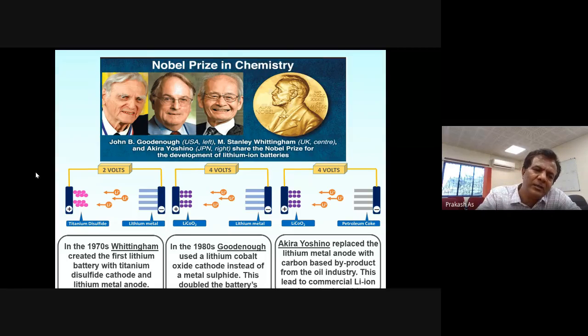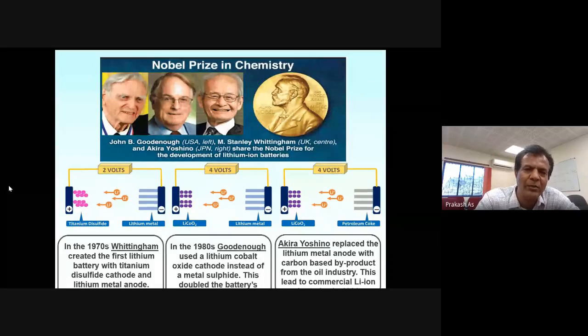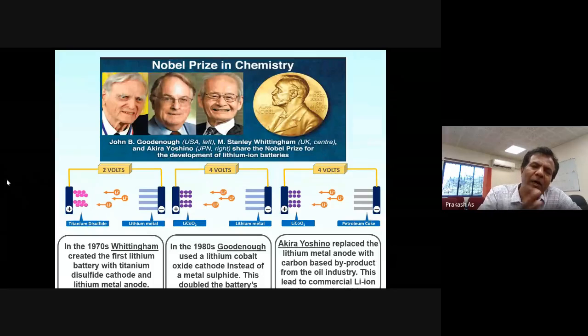And in this titanium disulfide, what happens is titanium is typically in the 4+ oxidation state. Titanium metal is 0, titanium disulfide is 4+. When you intercalate lithium into titanium disulfide, you have a redox of titanium, and this happens around 2 volt. So by doing that, he showed 2 volt across lithium metal and TiS2. This was the first demonstration of lithium in batteries.